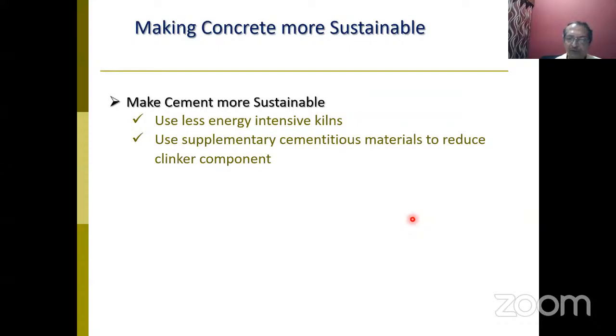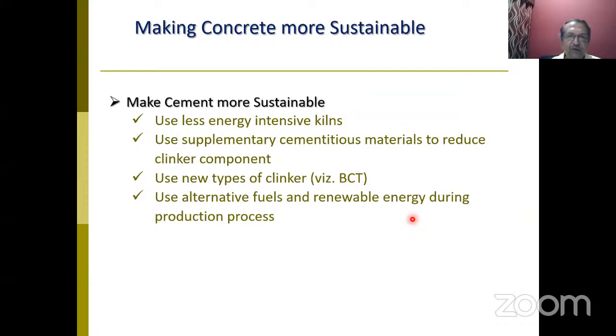So one is to make cement more sustainable so that we produce more and more blended cement rather than ordinary Portland cement, and keep ordinary Portland cement reserved to only where you require certain high strengths and high performances in structural requirements. Anyway, there are also possibilities that we use new types of clinker. So there are belite calcium sulfoaluminate ternesite blends which people are looking at, which gives you a totally different type of clinker which has lesser carbon dioxide footprint. And also to use alternative fuels and renewable energy during the production process.